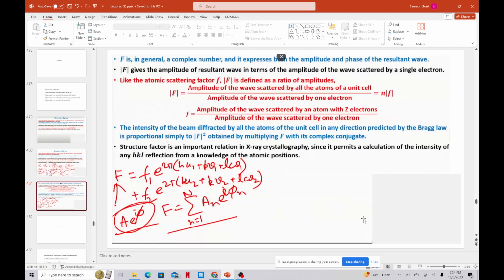Now this structure factor is a complex number and it expresses the amplitude and the phase of the resultant wave. Its magnitude, or the mod, gives the amplitude of the resultant wave in terms of the amplitude of the wave scattered by a single electron. Like the atomic scattering factor, it is defined as a ratio of amplitudes. So what is the structure factor? The amplitude of the wave scattered by all the atoms of the unit cell divided by the amplitude of the wave scattered by one electron. And f is what? The atomic factor. It is the amplitude of the wave scattered by an atom with Z electrons divided by the amplitude of the wave scattered by one electron. So the structure factor F is the sum of n times the atomic factor.